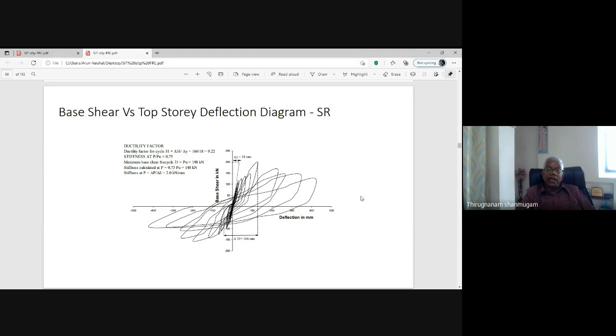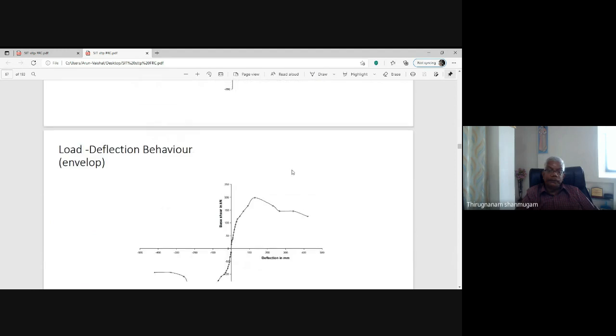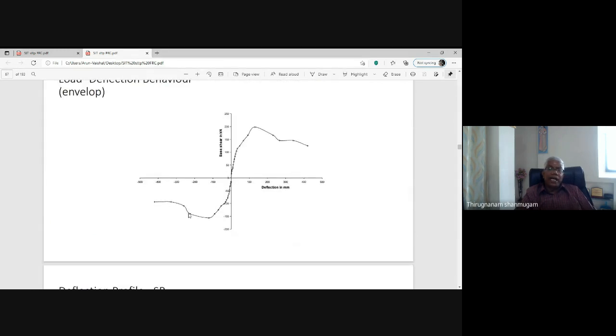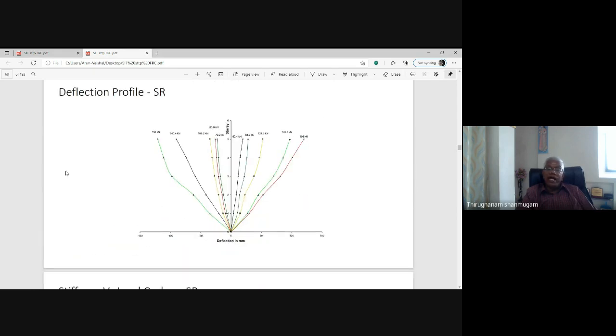Initially the stiffness is higher, and as the loads increase in the cycles of loading, the stiffness is gradually decreasing. That is called stiffness degradation. For the load deflection behavior, only the maximum load and maximum deflection are taken and plotted like this. It is the typical load deflection behavior of the frame subjected to cyclic load. For the deflection profile, we are measuring the deflections at the 5th, 4th, 3rd, 2nd and 1st stories, etc. When you plot the deflection profile, 62 kN, 83 kN, 124 kN, 145, 198, etc.